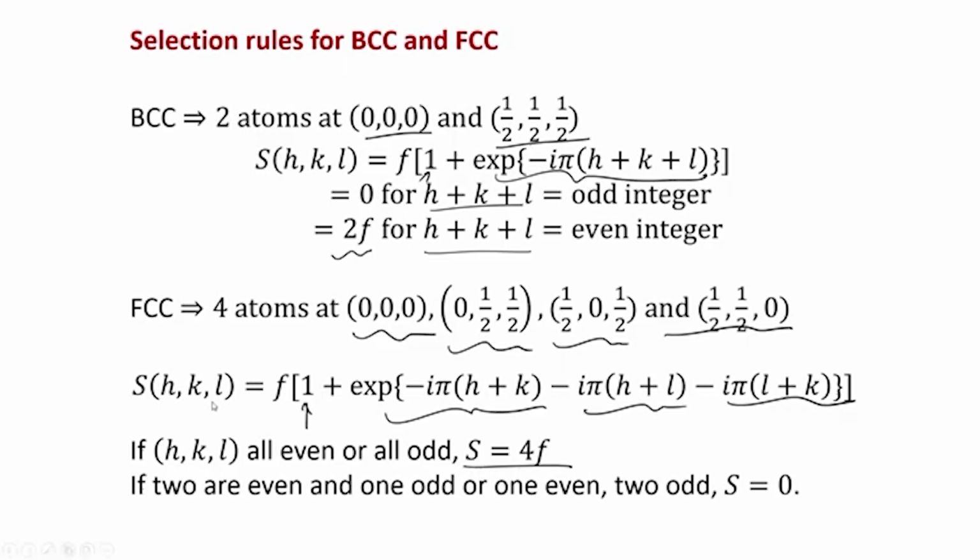So that is the selection rule, and it tells you about the magnitude of the intensity on the y axis, at least the proportionality. It will tell you which planes are capable of scattering X-rays, and then one assigns these h k l indices to the planes and can figure out what the crystal structure is.